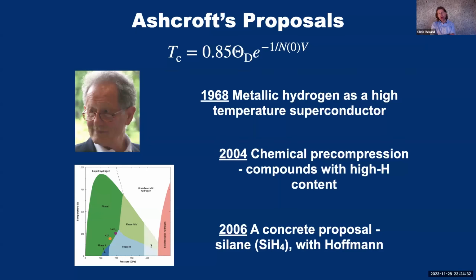But the key thing from here was that if you want a high Tc, you're going to want to have a high Debye temperature. And so Neil Ashcroft suggested that hydrogen could give you access to that, because the frequencies of vibration of hydrogen, because of the lightness of the hydrogen, could be very high. But it turned out to be difficult to find metallic hydrogen. So later on, Neil Ashcroft suggested, both in 2004 and a bit later with a concrete suggestion in 2006, that maybe we could achieve this effectively metallic hydrogen, but through forming a compound or some chemical pre-compression with other elements. And his concrete suggestion with Roald Hoffmann was that silane might be a good place to start.